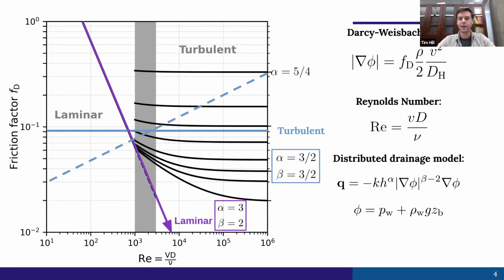I also want to point out that what's sometimes used in the literature is a smaller value for alpha that gives you a positive slope. It's not supported by the pipe flow data, but there's also, of course, such a difference between lab experiments through pipes and the actual subglacial drainage system. But anyways, what I would really like is something that transitions from laminar flow to something like turbulent flow at appropriate Reynolds numbers, and maybe having a smooth transition is going to be useful for numerics.